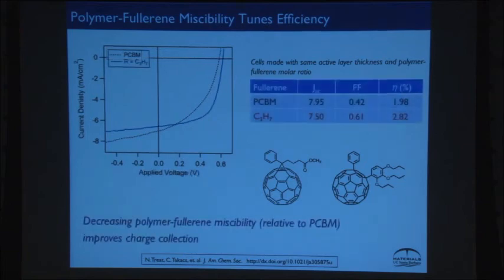So then we went and made solar cells with these. And sure enough, the student did this very apples to apples. He tried to keep all the processing the same just to look at the role of the fullerene. And sure enough, we got a big jump in the fill factor. The short circuit current varied a little bit. If we put error bars on this plot, they would be about the same. But the fill factor was always substantially higher. And we got a jump in the power conversion efficiency that was solely due to the fill factor.